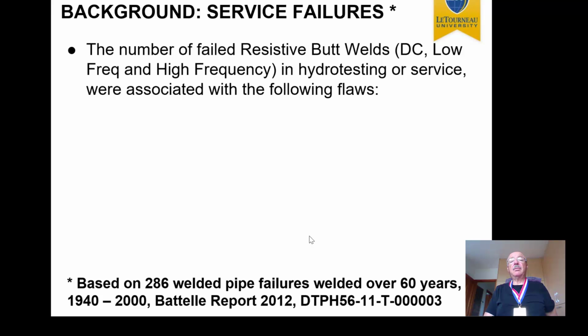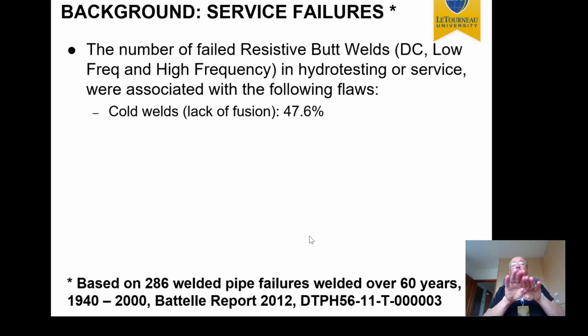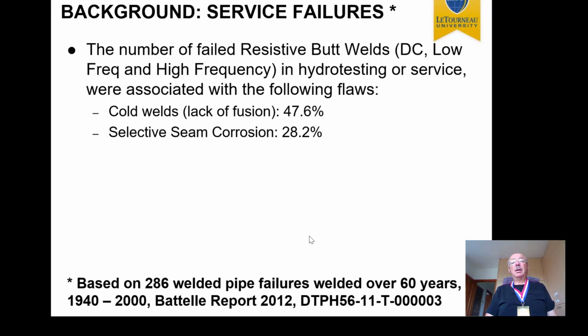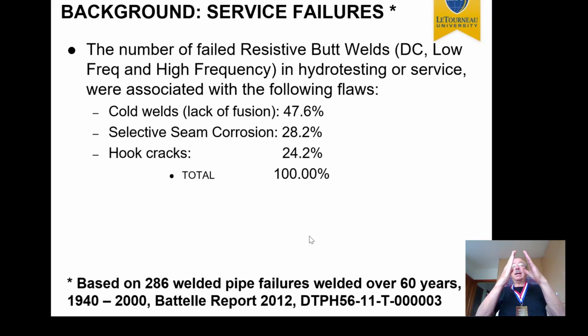So basically these pipes either blew up in hydro testing or in service, and about half of them were caused by cold welds. In other words, the edges were not squeezed together properly, there was no bonding, there was an oxide layer in. We talk about a flaw; we call them lack of fusion. There's seam corrosion when, again, the edges did not bond properly and corrosion occurred along the center line. And then there were so-called hook cracks, which were about a quarter of these. They were lines of non-metallic inclusions from steel production, which actually came apart. That's basically the three types of defects they found.